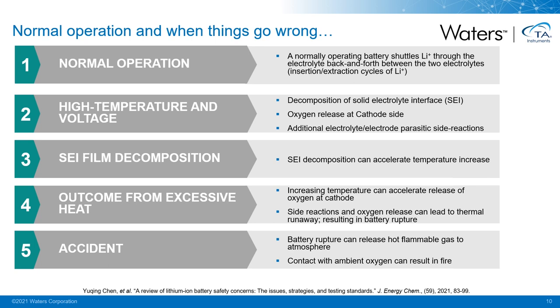What happens if things go wrong? If the battery heats up too much, you get a breakdown in the SEI and potential oxygen release, plus chemical side reactions. Some of these are called parasitic reactions because they rob the battery of its normal electrochemical reactions that fuel power production and storage. If the temperature increase gets out of control, side reactions, parasitic reactions, and SEI decomposition can accelerate, leading to unwanted liquid and gaseous chemical components. If too much gas is produced, the battery can expand and rupture, and some hot gas can be flammable. Management strategies include passive and active liquid-cooled temperature management, and additives that suppress side reactions and flammability. This study will use mass spectrometry paired with GC and LC to follow volatile and non-volatile chemical components.